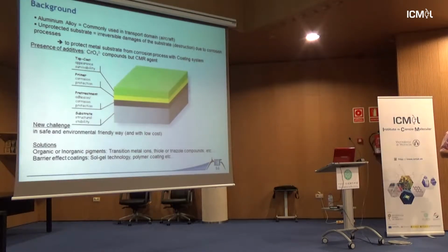So it's aluminum alloy. That's of course of interest because it's the metal alloy used for airplanes, and it's 2024. So its weak point is that it has some copper in the alloy, and the idea, of course, to protect this alloy from corrosion is to put in the primer. We call that the primer coat. So you have the substrate, the metal substrate. You have corrosion protection, apart from that, by electrochemistry, and after you have different polymer coatings. So the primer and the top coat.